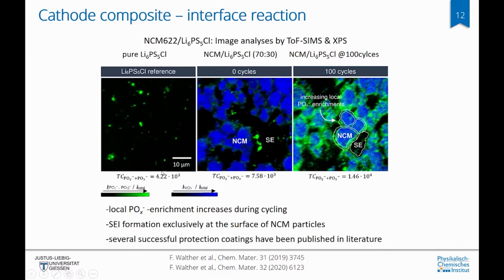On the left panel, you can see the SIMS analysis, so the phosphate impurity highlighted in green, which are present in the thiophosphate. And in the middle, present in the thiophosphate with NCM in blue in the composite cathode before cycling. And there only little degradation can be observed. But the situation is much changed after 100 cycles, when especially at the interfaces, a lot of green highlighted areas are visible, which symbolize the phosphate. So the thiophosphate has been oxidized by the NCM cathode active material at the interfaces.